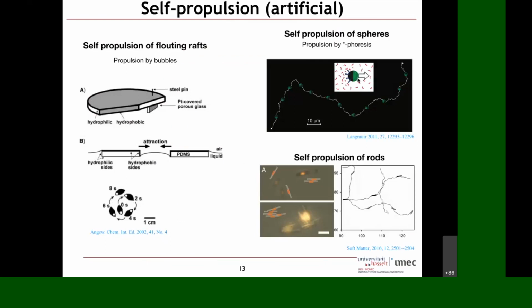One is you take a sphere, you coat half of it with platinum, another half is just a polymer, and then you put it in hydrogen peroxide solution. They start propelling because you're breaking the symmetry, right? One side there is a reaction, other side there's no reaction. You create oxygen molecules, and there's a diffusion gradient between oxygen rich and oxygen poor sides of the particle, and that kind of moves the particle in one direction.